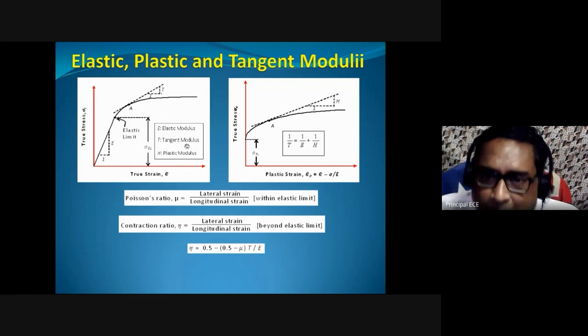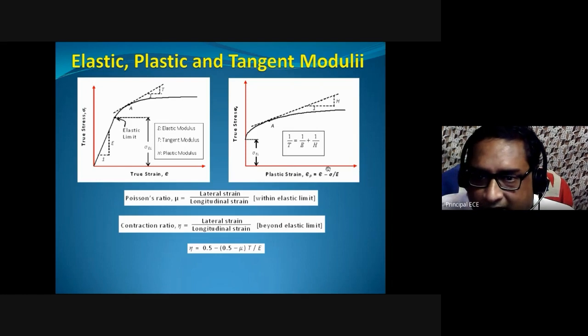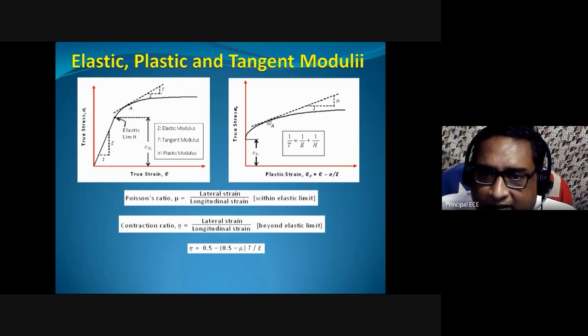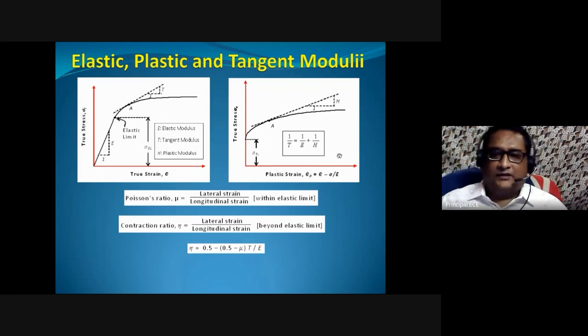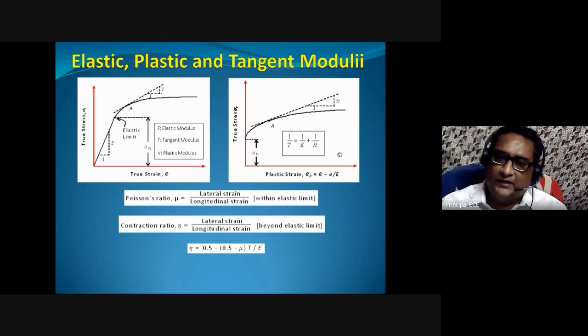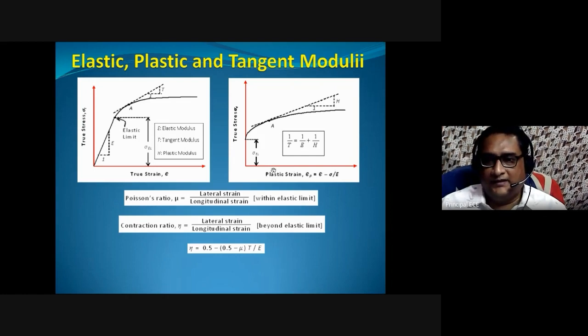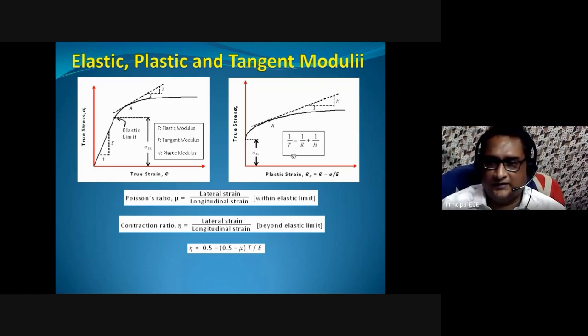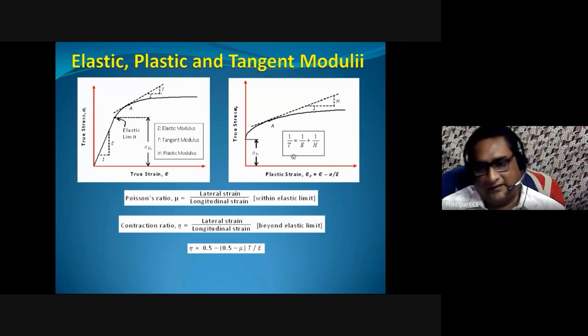So we have plotted in the next graph the true stress versus the plastic strain. This is the point A, at the same stress level. If you draw a tangent, that is called the plastic modulus H. And from the theory of plasticity, we can easily derive this equation: 1/T = 1/E + 1/H. This equation is required for design purposes later on.